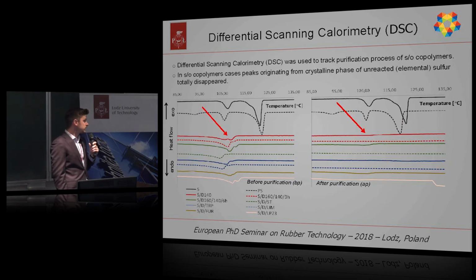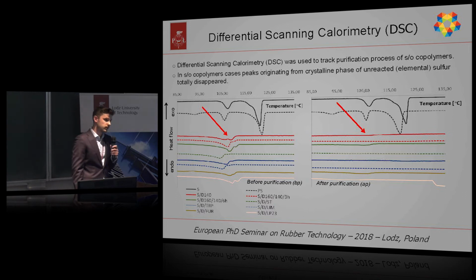When it comes to the DSC, I use this method to track the purification process of sulfur organic copolymers, because as you can see on the thermograms at the left side, some peaks originating from crystalline phase of unreacted sulfur exist, and after purification the peaks totally disappeared, so the purification process was successfully performed.